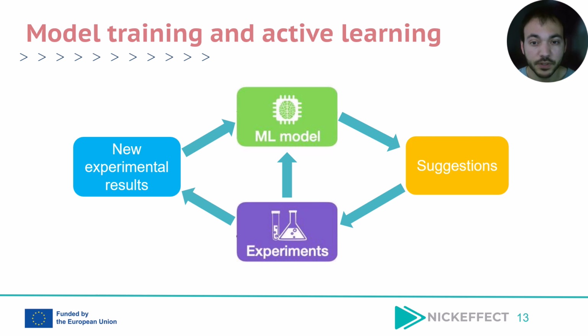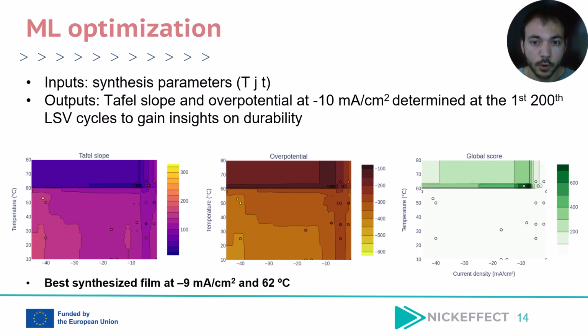Finally, with the help of machine learning, we devised a method to optimize the catalytic properties of the films and durability. First, we fed the obtained data from previous results, and after the calculations, the machine learning suggested more experiments to look for the best deposition conditions. We optimized the current density and deposition temperature to obtain the lowest Tafel slope and overpotential at minus 10 milliamperes per centimeter square during measurements, both at the first and 200th cycle, to also obtain insights on the durability of the material. In these graphs, you can see the actual measurements and how the program nails down the best parameters.